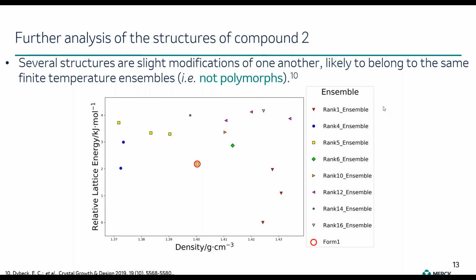Basically, they would crystallize in the same structure at finite temperatures. And this analysis greatly simplified the landscape, because we noticed that, for example, the three lowest energy crystal structures are very similar to one another, and they would likely crystallize as one in the solid state at finite temperatures. And also some of the crystal structures higher in energy are very close to our match to the known form.